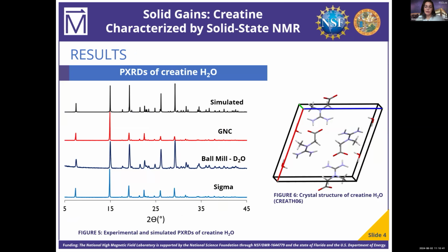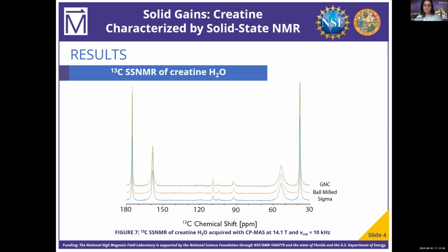First, we acquired the powder X-ray diffraction patterns of creatine monohydrate from GNC in red, Sigma in light blue, and a deuterated version, which we ball milled in the lab in dark blue. Comparison to a simulated PXRD pattern confirms these solid phases are all the same. Then we acquired carbon-13 solid-state NMR spectra of each of these solid forms and found they had similar carbon-13 chemical shifts and showed no signs of impurities.